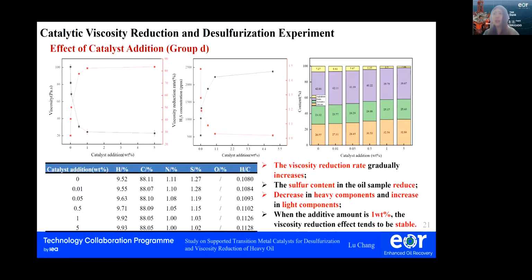Finally, we investigated the influence of the amount of catalyst on viscosity reduction. Group D was taken as the research object, and the experiments were conducted at 280 degrees centigrade. The result shows that with the increase of catalyst addition, the viscosity reduction rate gradually increased, and the sulfur content in the oil sample decreased. The heavy component decreased, and the light component increased in the oil sample. The viscosity reduction effect tended to be stable when the addition amount was about 1 weight percent.